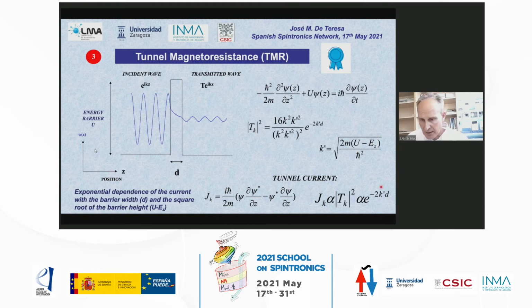And this is different from zero, so we can have tunneling of electrons from one side of the barrier to the other side. So if you calculate the tunnel current, you will see that it depends on some transmission probability, and then an exponential dependence on the barrier width and on the square root of the barrier height.